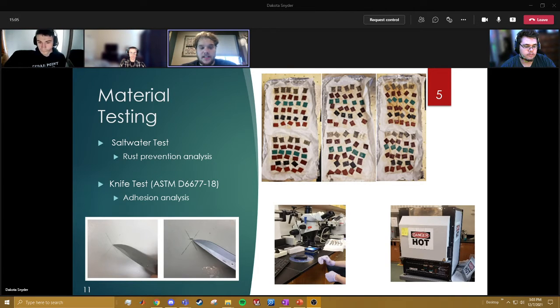The team sprayed e-steel coupon samples with each material. These samples were temporarily submerged in a 5% by weight saltwater solution, then baked at 140 C for 40 cycles at 10 minutes apiece. This saltwater test advances the rate of corrosion and allowed the team to analyze each coating's prevention capabilities. The knife test is an industry standard used to analyze coating adhesion performance. A knife cuts an X into the coating, and then the coating is pried upward using a known force. Strong adhesion is an indication of good coating performance and will help prevent corrosion.